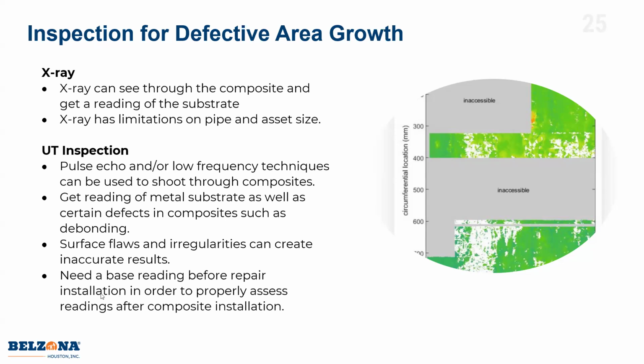One of the main things to consider with the UT inspection is that you really want to get a reading of the metal substrate before the repair. That's going to give you your metal reading. Then you get a reading right after you install the repair. That's going to give you your repair plus substrate reading. And now you have the baseline to inspect it in 10 years or 5 years. Because if you only do one in 5 years, you don't know: when you get no reading on the UT, it could mean two things. It could mean a hole in the pipe, or it could mean a debonding of the composite.